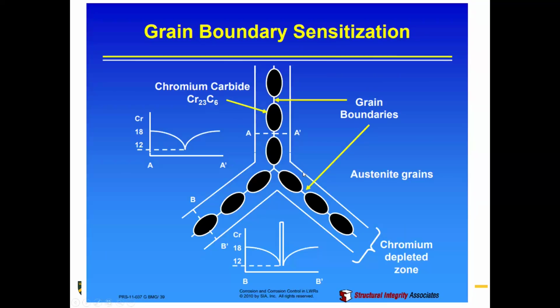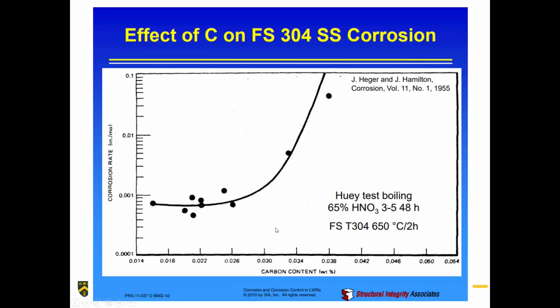Okay, just a recap here: at those grain boundaries, you're forming those chromium carbides. What ends up happening is that this is heavily controlled by a number of different constituents of the metal. 304 stainless steel is primarily where we saw this issue. One of the things that controls that is the actual carbon content within the stainless steel. There's a range within 304. For those higher carbon content variations of 304, you saw this much, much worse, particularly if welding was taking place, because you saw much more readily those chromium carbides forming, and so much more readily the attack at those grain boundaries. You saw this very obviously when you have a higher carbon content within the steel.